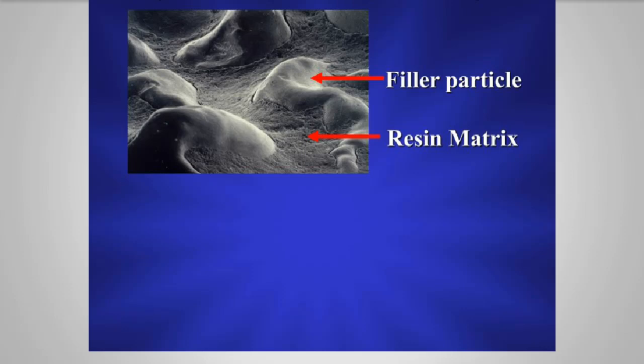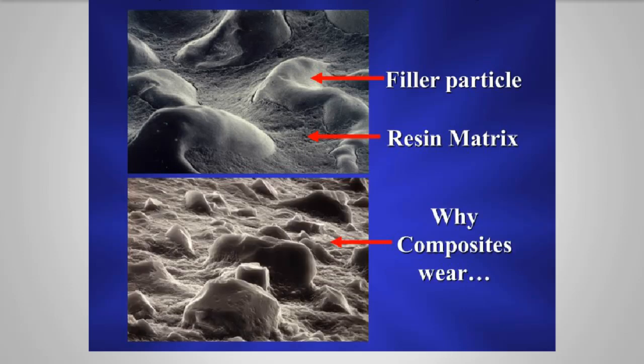And this is what the surface of a newly placed composite might look like, and here's what that same surface might look like after some time in function, maybe after a couple of years in function. And this, by the way, is a primary reason that composites wear. The resin, which is much softer than the filler particles, wears to a much greater extent, and after time the filler particles begin to stick up out of the resin matrix, as we see here, and can be lost or plucked out of the resin matrix, resulting in a hole or void.